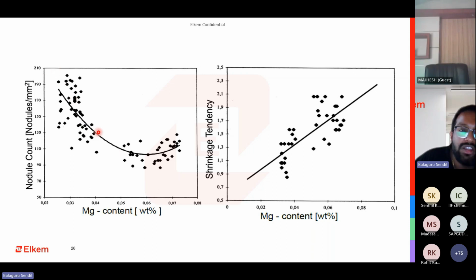When the nodule count comes down, the possibility of getting shrinkage, intercellular carbides, and inclusion kind of defects becomes much higher. So it's always advisable to have the correct residual Mg, not more than 0.045. This range is the most perfect target. And again, what happens is how is your shrinkage tendency? If you are on the higher side, both are correlatable. If it goes beyond a certain level, then you will also end up getting shrinkage. So it is not advisable to use the highest amount of magnesium at the lowest addition percentage with a high residual Mg of 0.06, 0.07. That is also not a very mechanically or metallurgically viable process.